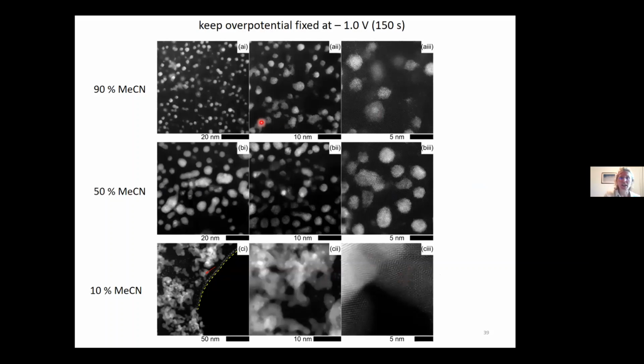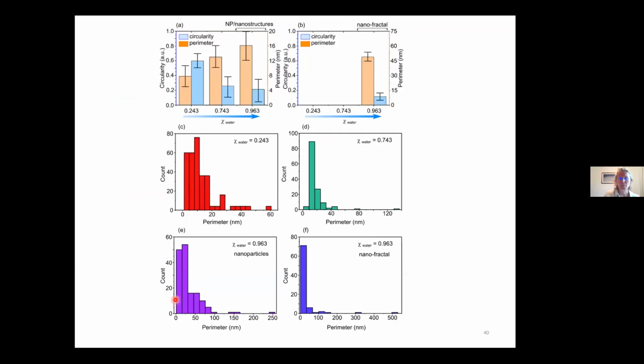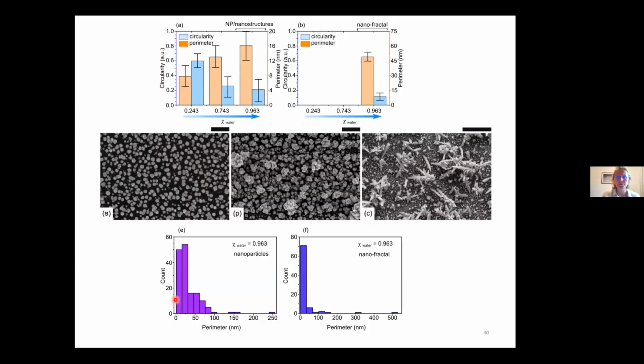for different mole fractions of water with acetonitrile. And again, organic rich, mostly nanoparticles. The mixture, you see the coalescence events, and then the water rich, you really start to go to this almost very much fractal dendritic growth. And we can represent this with statistics. So again, statistics is, as I said, really important with microscopy, that you try and represent as best you can what's going on over a large area of the surface by looking in many different zones.